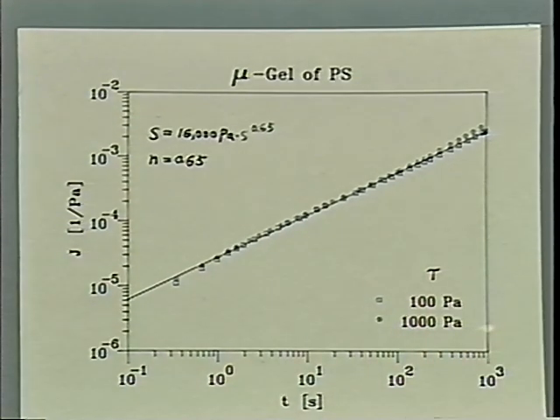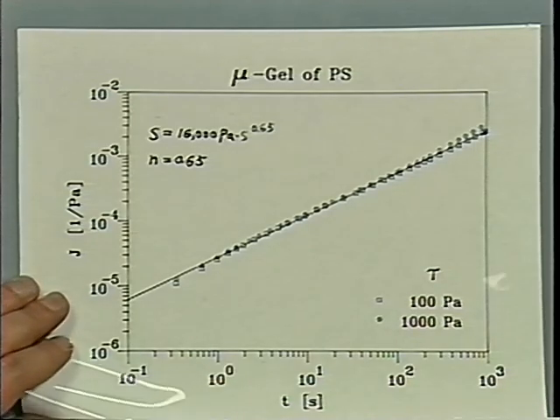You know, when just taking one value for S for the form factor, one value for N, and then all the data are consistent. We can check between creep, startup of shear or dynamic shear or the relaxation modulus, and all of this fits very nicely. Those microgels behave like a material at the gel point. And if we would know why, we would know quite a bit about molecular dynamics. Something for you to solve. You know, some puzzles are left over. Okay.